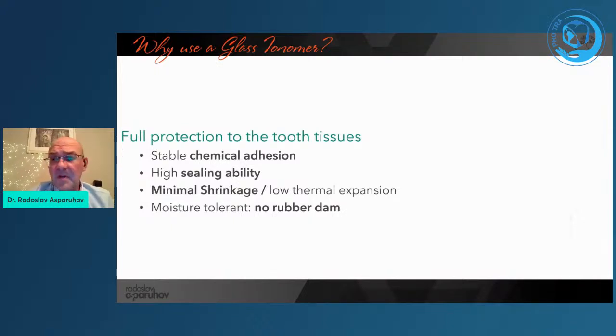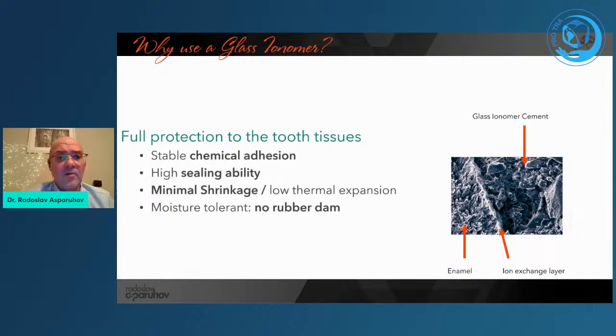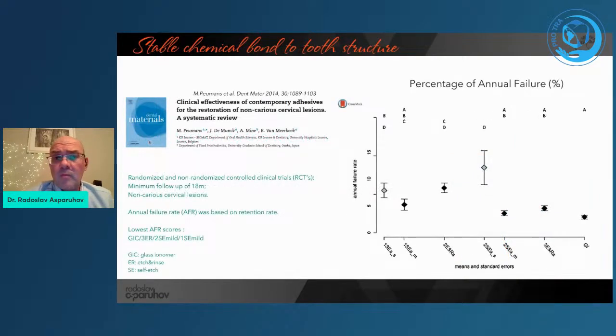So to summarize, why we use glass ionomers: because of the chemical adhesion, because of their sealing ability, because of their minimal shrinkage and low thermal expansion, and because they are moisture tolerant, they do not require rubber dam. One might argue that glass ionomers do not have a higher bond strength to the dentin or the enamel, but that is irrelevant, because when we look at the percentage of annual failure rate, you can see that glass ionomers are performing as well as the best adhesive systems, which are usually two-step etch-and-rinse adhesives.